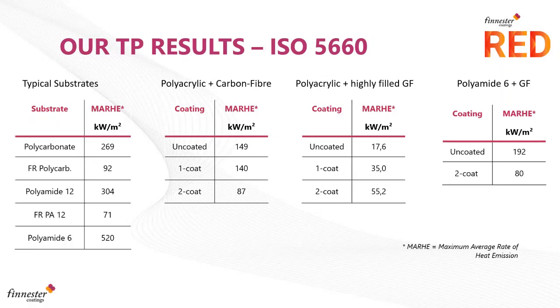And the polyamide 6 on the right-hand side, that final set of results, again reaching hazard level 2 from an uncoated MARHE number of 192. So very significant improvements in reducing this rate of heat emission and meeting the EN 45545 standard.